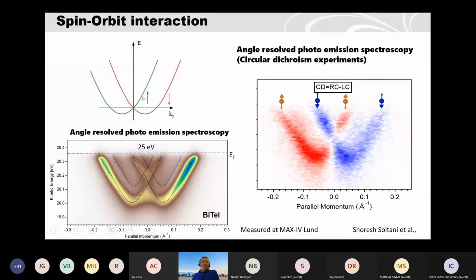How to know the spin polarization, whether spin is up here or down here? You can do a circularly polarized dichroism experiment. You do a right circular light experiment and a left circular light experiment and subtract them from each other. Then you can get the spin sensitive data. The red ones here are, for example, spin up, and the blue ones are spin down. If you measure, for example, the silicon band structure, it will look only parabolic, one band. But if you measure such a material, you will see these split bands. And these properties actually influence the material behavior.